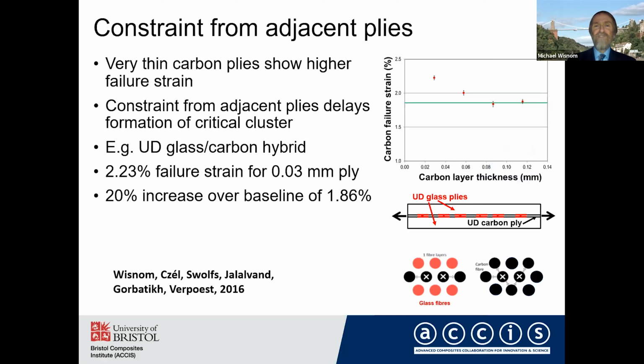Another factor which is not really well understood is constraint from adjacent plies. What we've shown is that very thin carbon plies can show higher failure strain by quite a significant margin. In this case here, I'm plotting some data from hybrids. So here we've got carbon plies sandwiched between UD glass. And what you see is that as the carbon becomes very thin, the failure strain increases, and it's not a small amount. The failure in this specimen here is 1.86% for the thicker plies. But as you get down to this ply here, which is only 0.03 millimeters thick, we've got 2.23% strain. There's a 20% increase in the failure strain over the baseline.